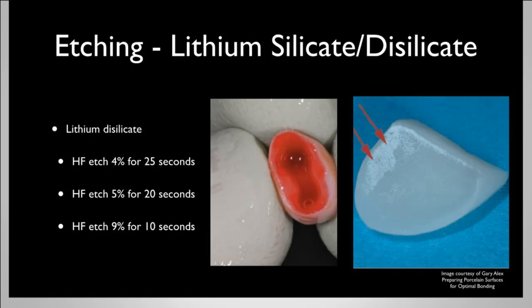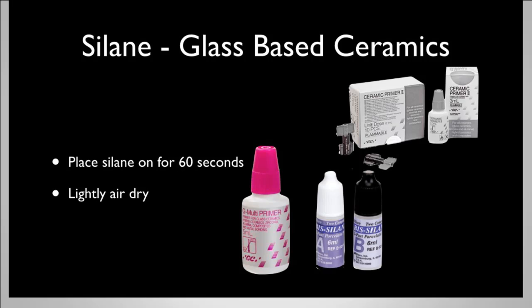With lithium silicate and disilicate restorations, we want to etch at much lower concentrations. We want to etch with a 5% solution for 20 seconds, or a 4% solution for 25 seconds. We do not want to have the long etching times we had in the past. And as this image by Dr. Gary Alex shows, when we over-etch, we can actually get a salt formation that can weaken the ceramic and decrease bond strengths.